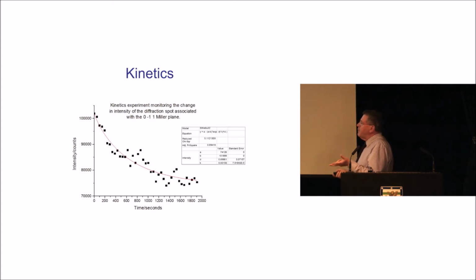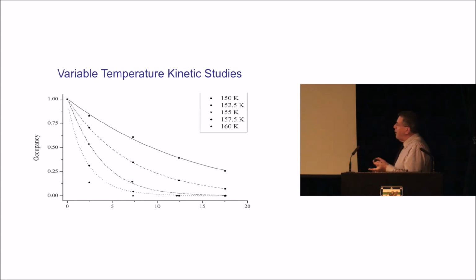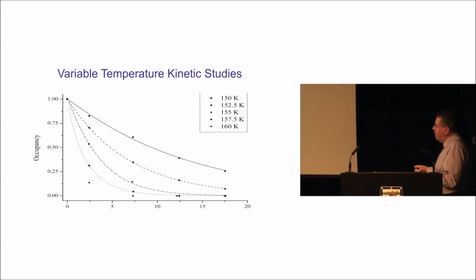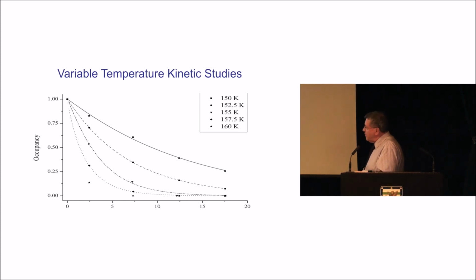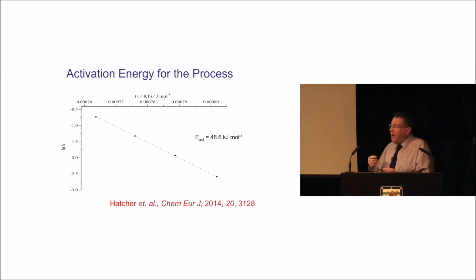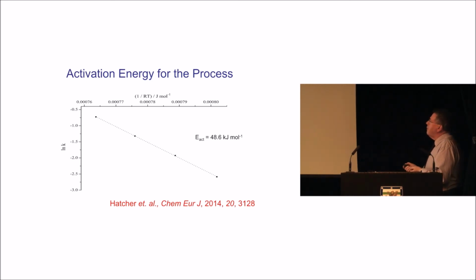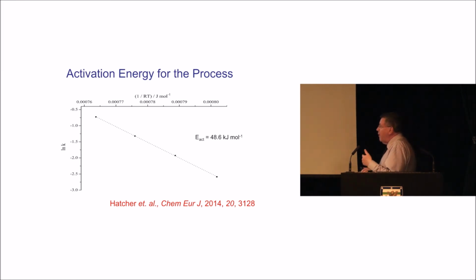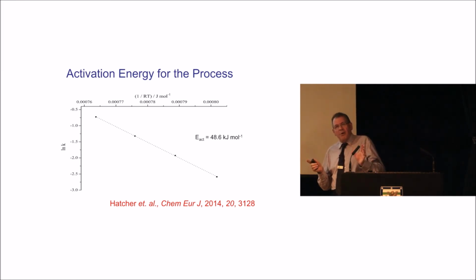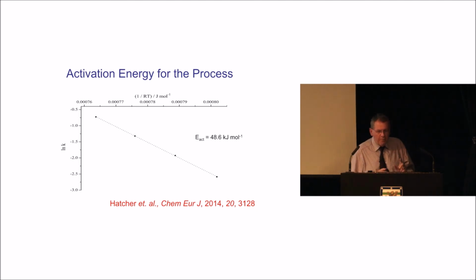What it also allows you to do is play with the variable temperature idea and start measuring kinetics at different temperatures, which allows you to determine the activation energy, and that comes out at 48.6 kilojoules per mole, which, I think, has the right feel. It's also in remarkably good agreement with computational studies that we've done.